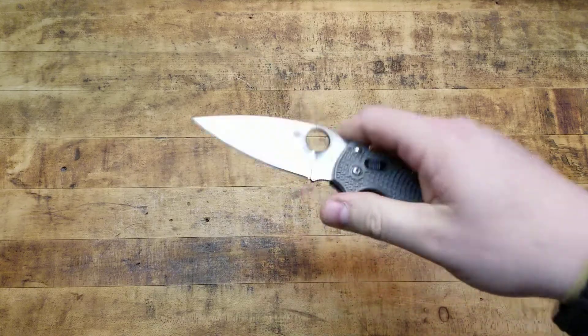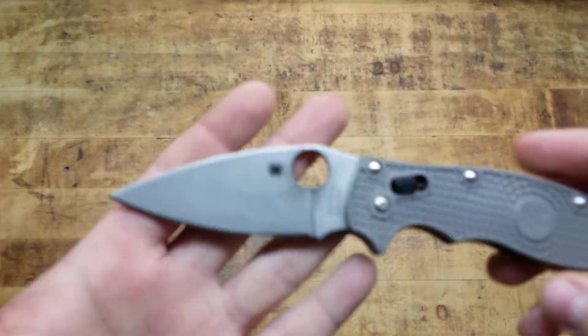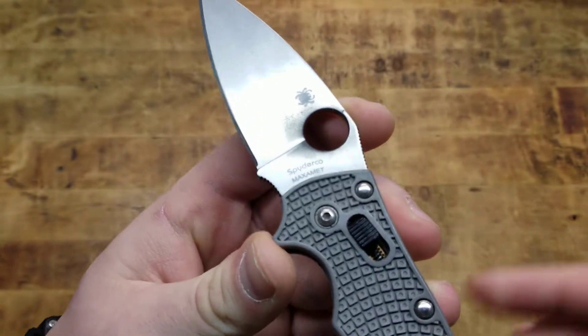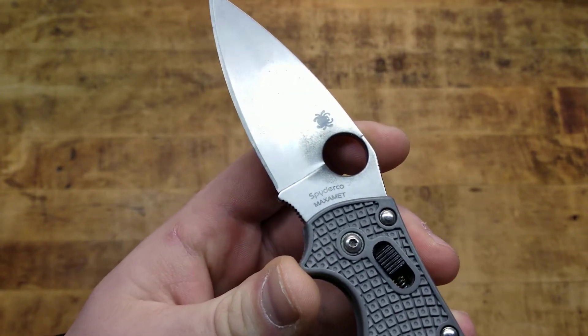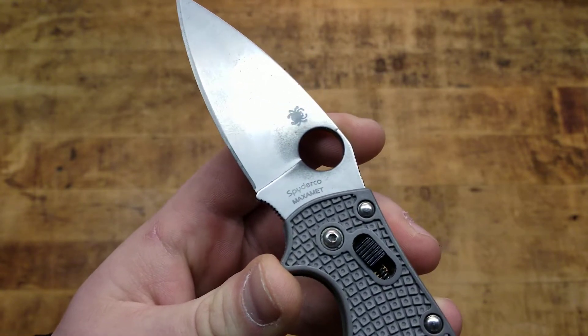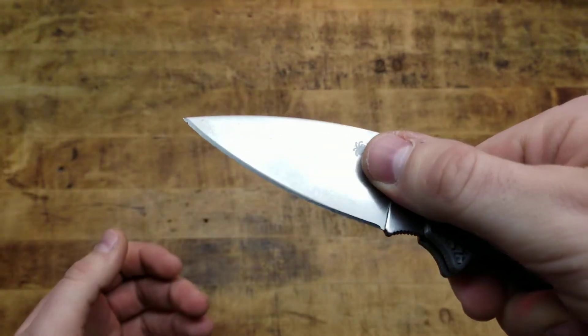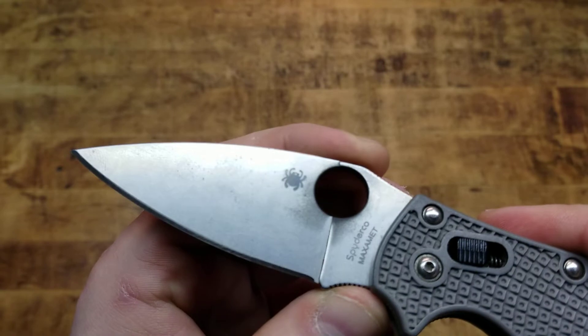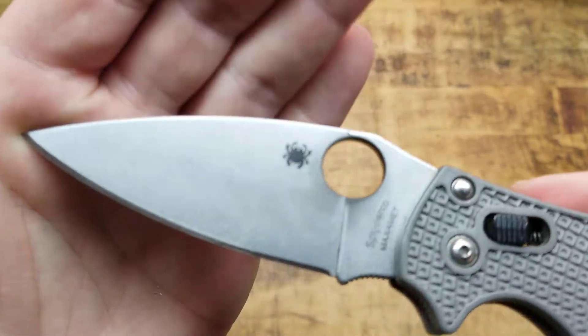I mean, it's a sharpened edge, right? You can use a blade for whatever you need to use a blade for. But this one being Maxamet, which is somewhat of a super steel, has very, very little chromium in it and that leads it to not be corrosion resistant. Just from the oils in my hand, from using this spidey hole, there is some patina there, some rust. You can see there's some surface rust all through the blade.